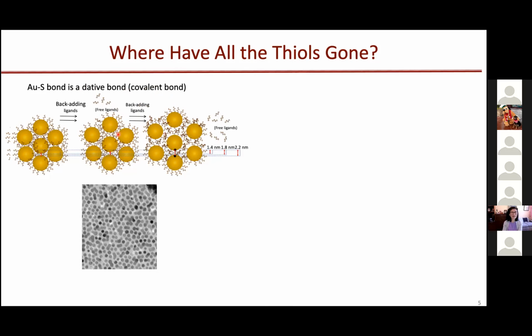However, this theory cannot explain why, when thiol concentration is very low, the gold cores stick together, meaning they're sintered and glued together. If you have fully ligated particles, they can't get close enough to glue like this.